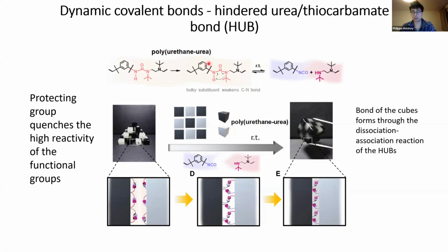And you can use this dynamic covalent bond to make, here we've made some poly(urethane-urea), and it has a dynamic covalent bond and can essentially switch between this state and the individual molecules. So this steric hindrance, this bulky substituent, weakens the carbon-nitrogen bond, and that causes the bond to switch essentially. So it always switches between the coupled and the individual components of those two.